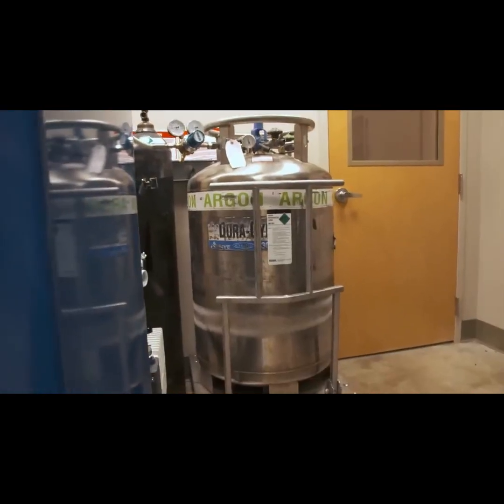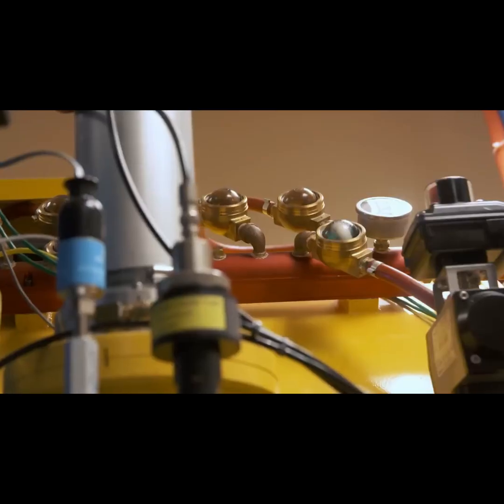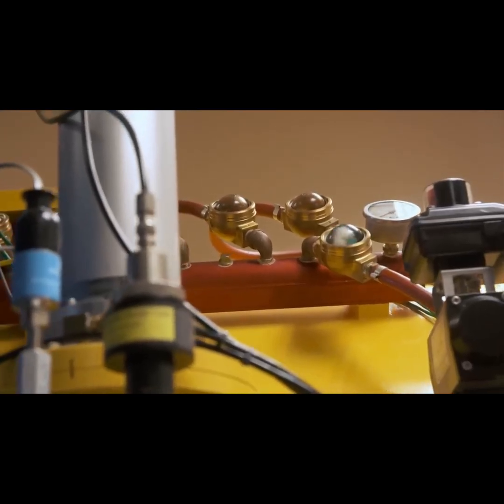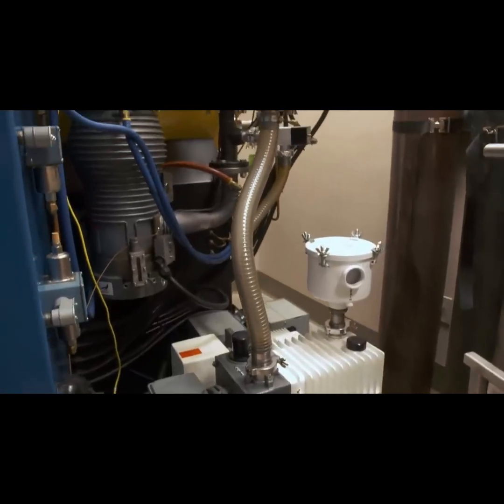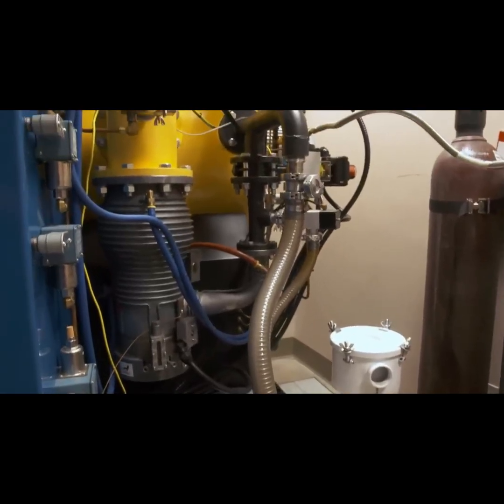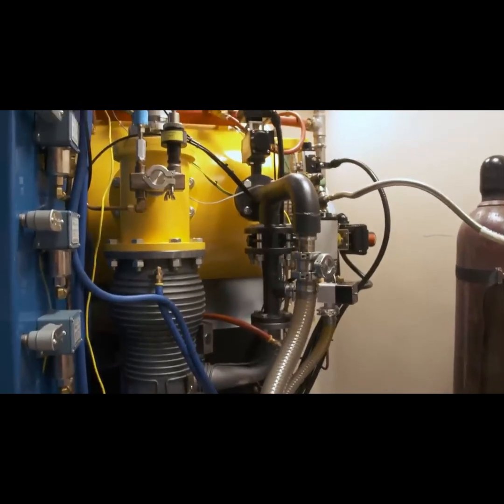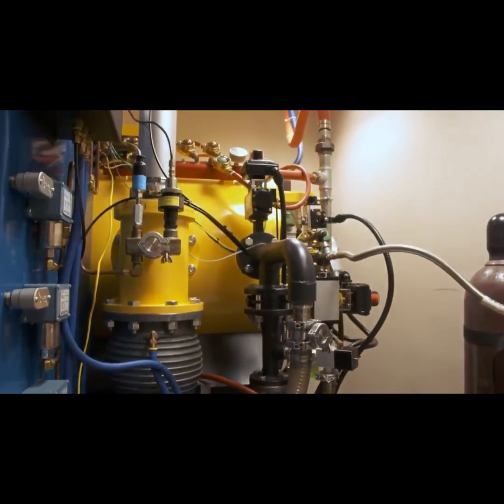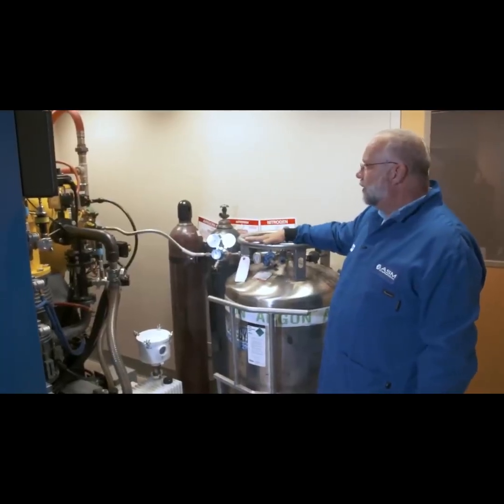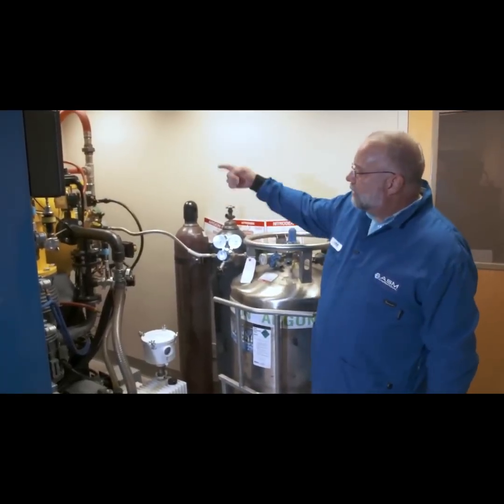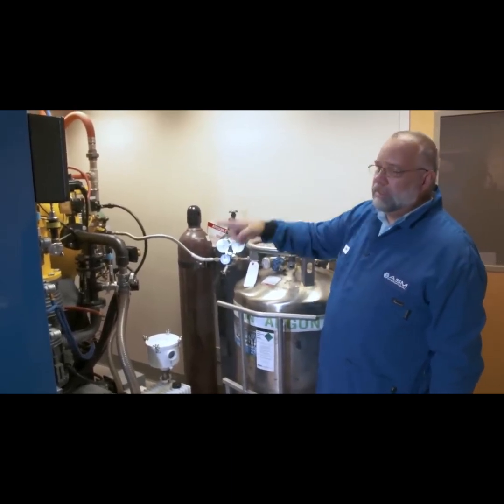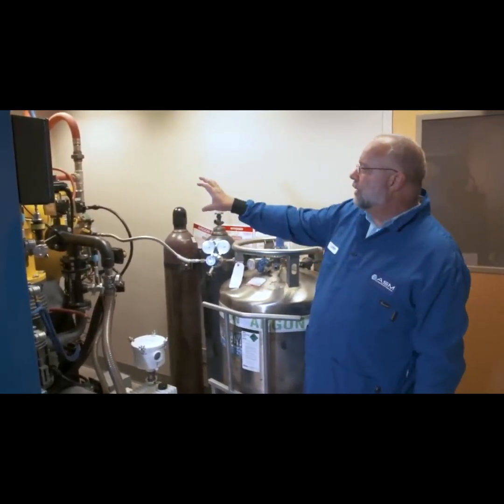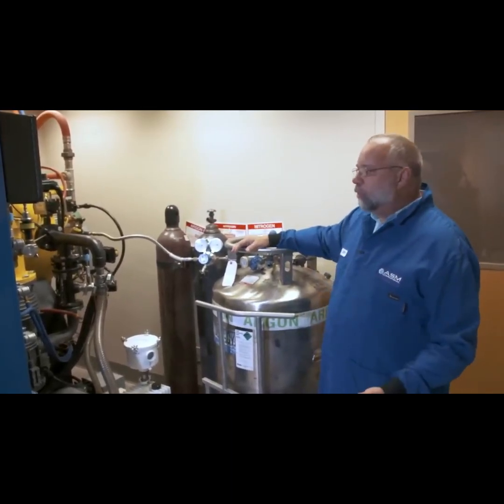We have it hooked up to a liquid tank of argon. We're applying about 100 psi to control the valves. It's a backfill. And then when we quench or cool down after that hold, we're going to get the argon in there as quick as we can. And on the back there's a fan that's going to be rotating the argon through the furnace and through a heat exchanger to do the cooling.